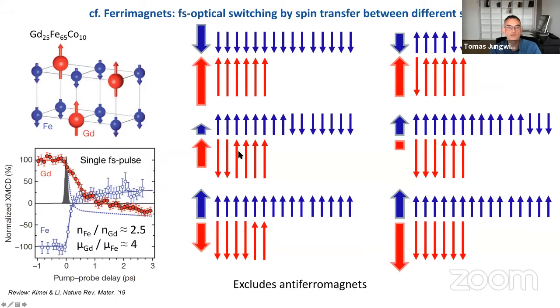But what you see here already on this cartoon is that you create a transient state which is not anymore antiferromagnetically coupled, but is ferromagnetically coupled. And indeed, this is something that has been observed in an experiment, that at this transient state, you already reversed the moment of the iron sublattice. When you continue, you flip the third moment of gadolinium, you again flip the next 4 iron moments. And what you get in this case is demagnetized gadolinium and already reversed iron sublattice. And once you then flip the next moment of gadolinium, you see that you complete the reversal. So this is a mechanism which works, for example, in this gadolinium iron compound here, but it clearly requires 2 different sublattices of a ferrimagnet, so it seems to exclude antiferromagnets.